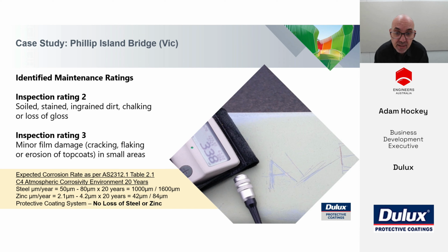If we had zinc-coated steel, we would expect that we would have lost 42 to 84 microns of zinc over that period. So it's important to understand when we're protecting steel and we're trying to provide a design life and a long-term protection, that whilst that coating system is in place, we've had no loss of steel or zinc. That steel or zinc coating is still in exactly the same condition as it was originally installed.